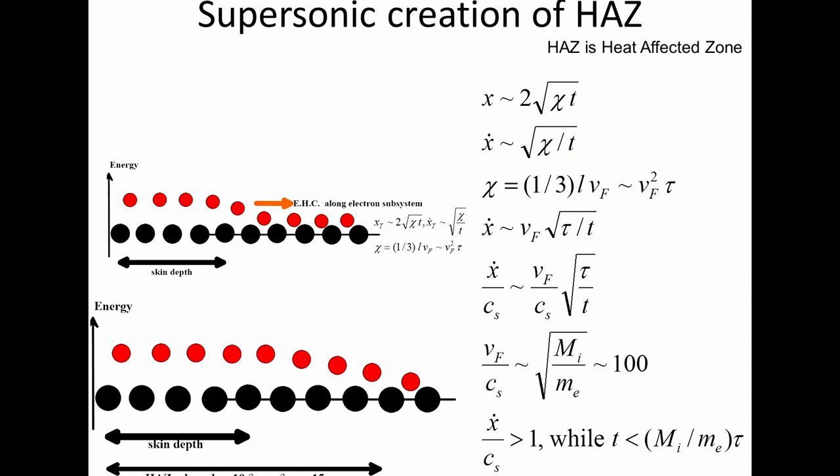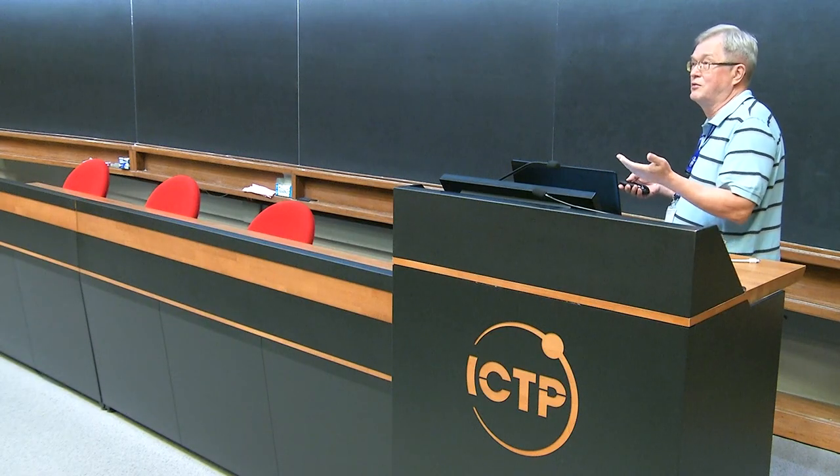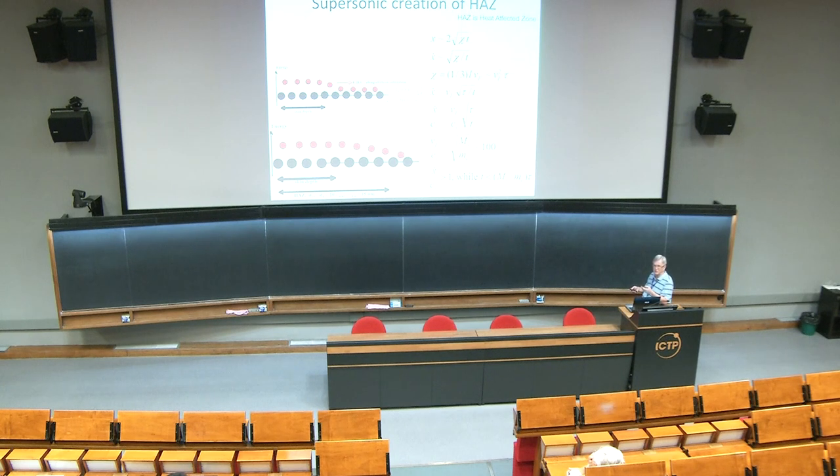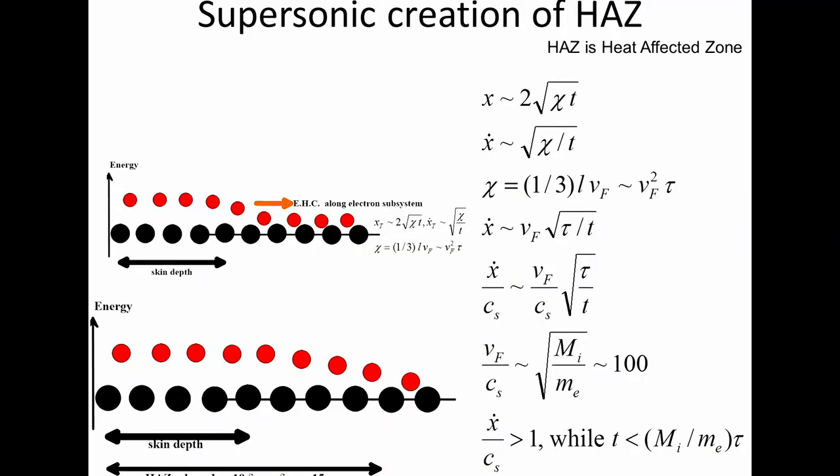And here I just write some simple expression explaining why it is supersonic. In usual conditions, heating is much slower than sonic acoustic wave propagations. The rate of heat transfer is usually subsonic, significantly subsonic, but in our case it is supersonic. This is just due to the fact that the Fermi velocity of electrons which transport this energy is two orders of magnitude higher than the speed of sound.